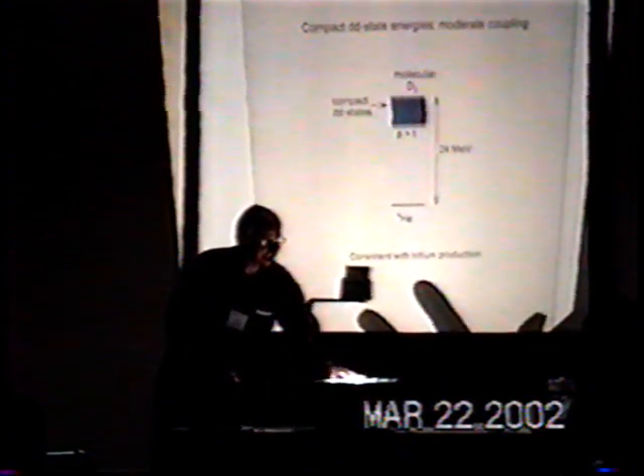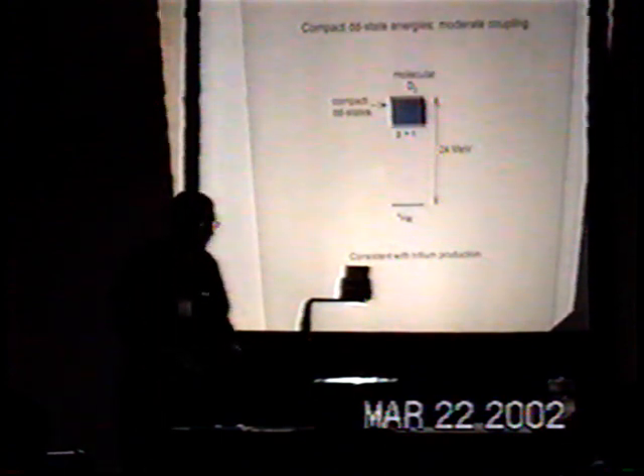This model agreed with the Chambers and Cecil results quantitatively in terms of state energies coming from different host lattices. If you have moderate coupling, so the state extends down about 4.5 MeV, since the compact states can exchange with the lattice rather efficiently, the deuterons can dump energy to go down to the proton plus triton channel. And you have a mechanism for making slow tritium, consistent with some of the results people have talked about today.